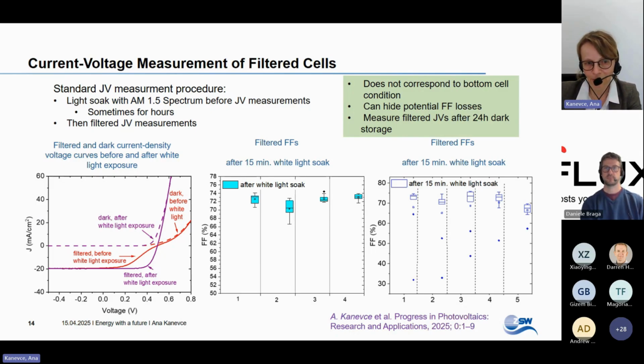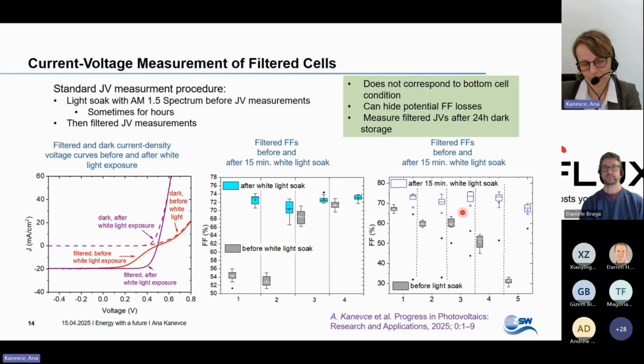For example, here are filtered fill factors of a series of cells which have seen 15 minutes of white light soak. All the fill factors look similar-ish. They are in the 70% range. Now the same cells were put in the dark overnight, and then fill factors measured again. Some cells are still okayish, other cells have really fill factor problems. So if we do light soak and then put a filter to do JV measurement, we can really not distinguish if we have a cell that would produce a low fill factor as a bottom cell, or that would work well.